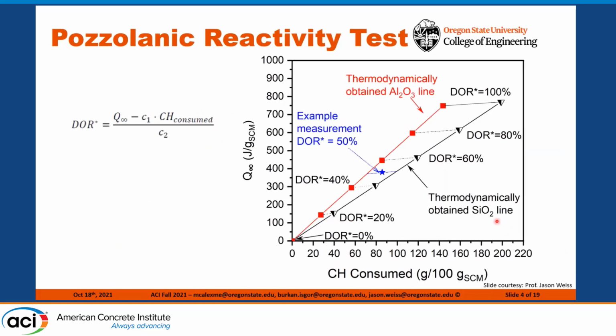The results of heat release in joules per gram SCM and CH consumed in grams per 100 grams SCM are plotted on the graph with reference to the ideal aluminum oxide and silicon oxide degree of reactivity lines. These reference lines are connected to indicate different DOR star values, and DOR star can be calculated with this given equation for each material, with the Cs being constants.